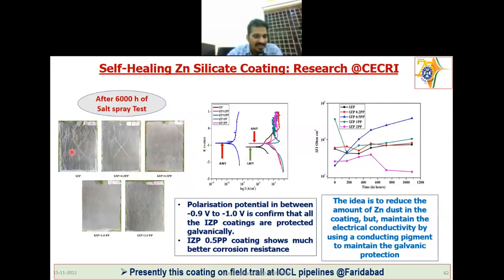This coating is IZP, that is without adding any pigment. The white rust is nothing but from the zinc, but you can see red rust here. This kind of red rust mark was not seen here. We developed this coating for IOCL, and right now it is in field trial at IOCL. Almost 9 months are over and we are yet to see any kind of corrosion spot on this type of coating.